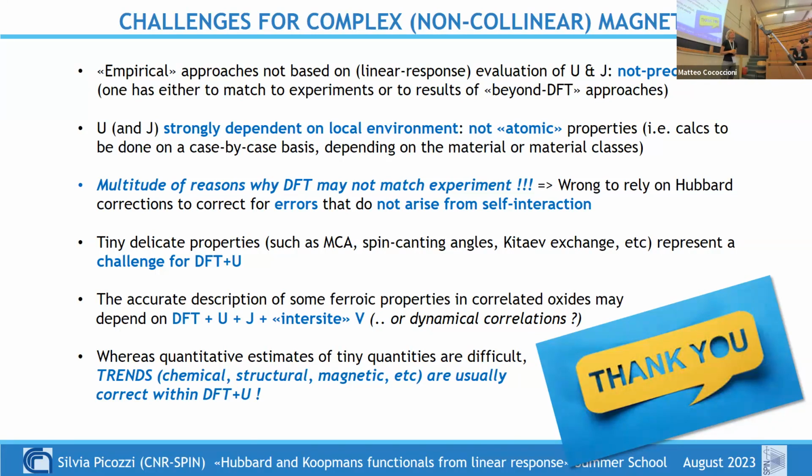It's hard. I think it boils down also to the Heisenberg approximation that you're doing, right? In Heisenberg, you're assuming from the beginning that your spin doesn't change. If I rotate it, it's fixed. But this is not true if you have a metal. So if I have something which is metallic in the ferromagnetic state, then I would say the Heisenberg picture breaks down. So if you're strict on that, then I think you cannot evaluate any J, right?